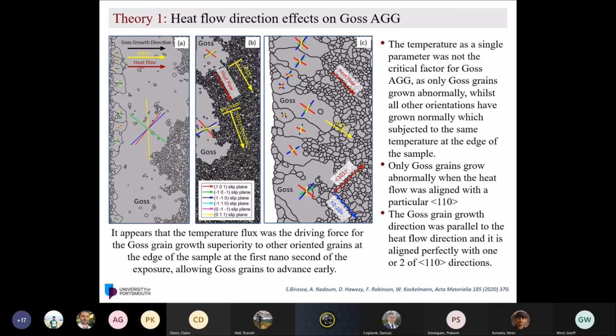So it appears to us that temperature is not the only factor for abnormal grain growth, because there were so many other grains around, with so many other orientations, but they didn't grow abnormally. That's what we tried to understand from a neutron diffraction experiment we did, and I'm showing it in the next slide.